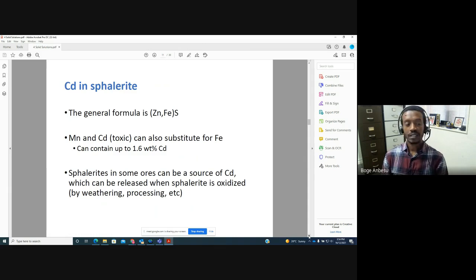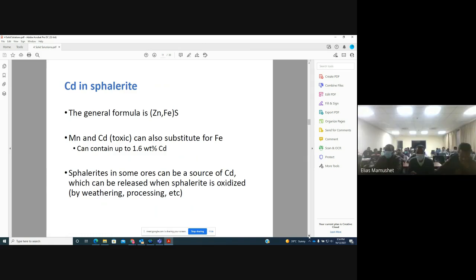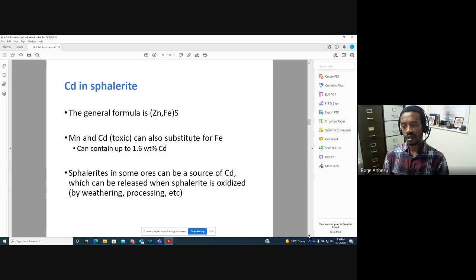Again, what's the big deal here? The big deal is if you have cadmium as an impurity, as a solid solution, then we know cadmium is toxic. When you're going to extract the zinc, you have to deal with the cadmium as well. Okay, especially if it's in high amount. And therefore it needs to be removed, it needs to be treated. And sometimes the cadmium can be really high in amount. You can actually produce a byproduct of cadmium, and therefore that can be a good thing. But typically, cadmium tends to be trace amount, and therefore it needs to be disposed of properly during processing.